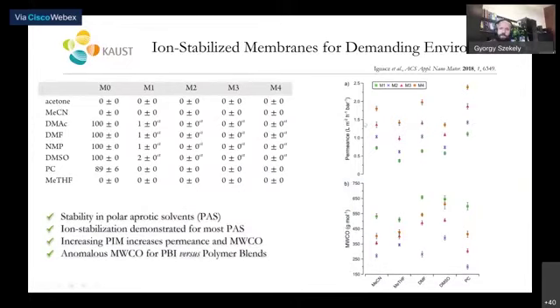Okay, so here you can see the permeance that we compared, and again the MWCO for the separation in different organic solvents. So these membranes were stable in polar solvents such as acetonitrile, methyl THF, DMF, DMSO, or PolarClean.